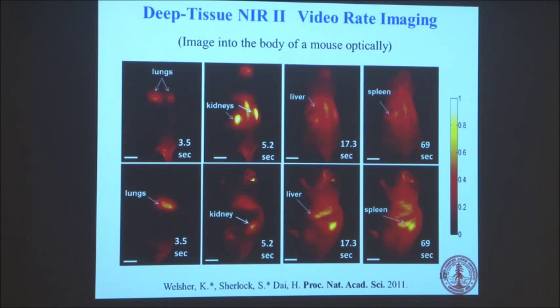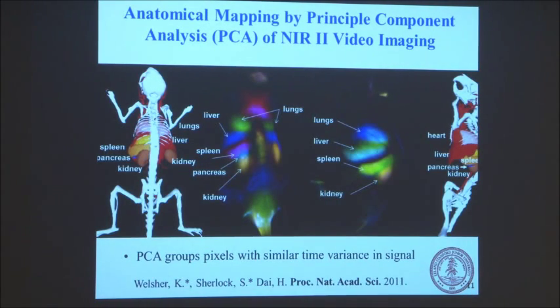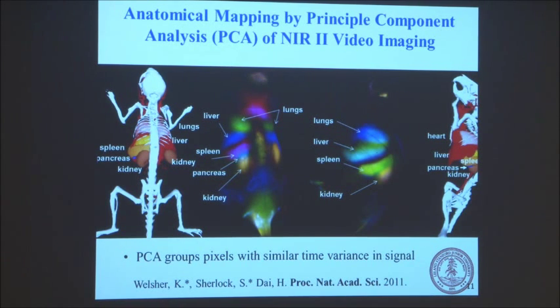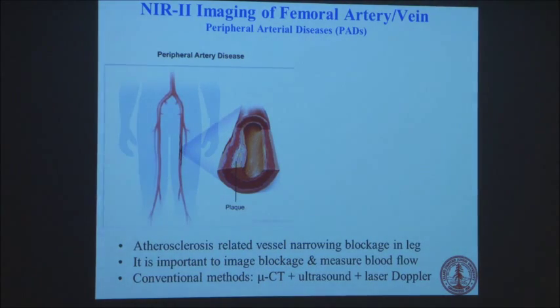Images like this give you a sense that the body is actually somewhat transparent because of this reduced scattering. We also did this analysis called principal component analysis, PCA, which basically groups the similar pixels together into the same color. So you can really resolve every major organ in the body by simple imaging like this. And most recently, we started to try to use this technique to see whether we can image important features in the body, such as the blood vessels, as I mentioned in the beginning.